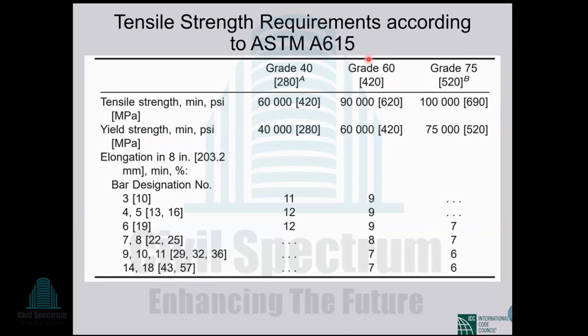But according to ASTM A615, there are 3 grades. Grade 40, you see, 280 megapascal, less than 300. Grade 60, which is 420 megapascal. That's why in ISO we also have one B420. And grade 75, which is more than 500 megapascal, 520, because 500 corresponds to 72.5 ksi. So there is a difference. So the B500 grade steel that we find in the market doesn't correspond to any grade of ASTM.